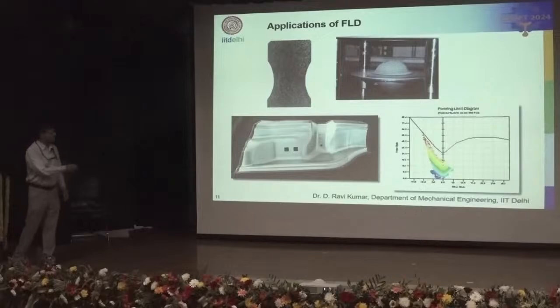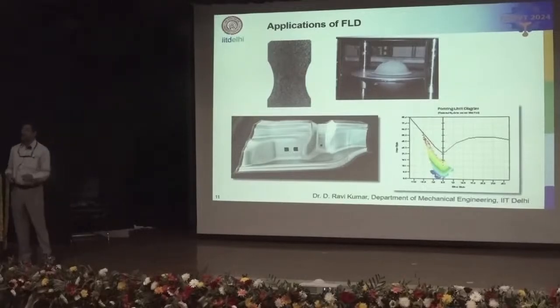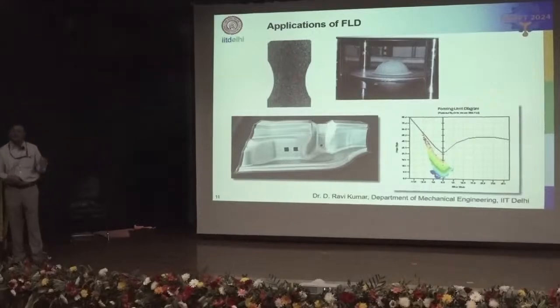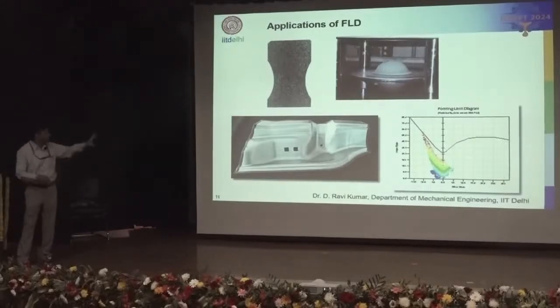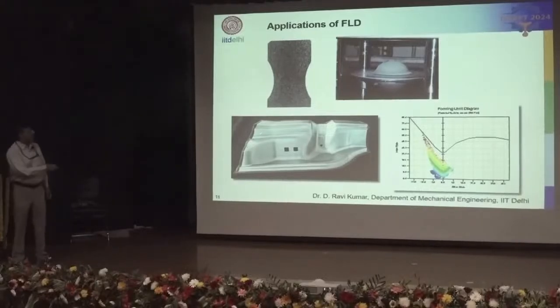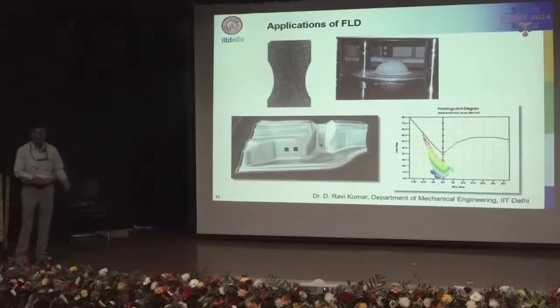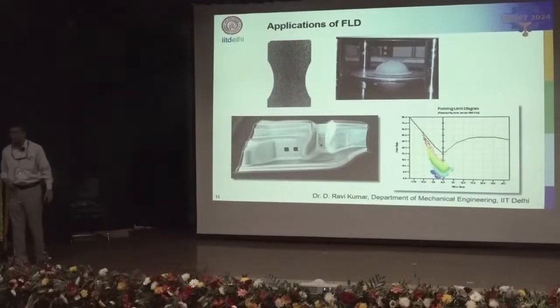There are two uses of this forming limit curve. One is to predict failure. The second one is to diagnose failure in case there is a failure in a certain component. So you can see here that there is a component and certain regions in this component are extremely critical. So what do we do in the development stage? We do laser grid marking or stochastic pattern on the component. We form the component. In critical regions we measure the strains, and those strains are superimposed on the forming limit curve, as you can see.